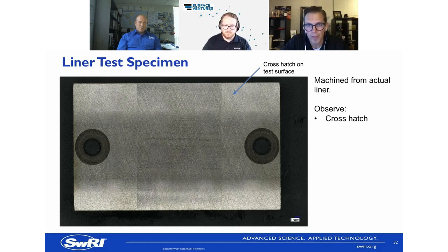And that was pre-run-in. Now with both coatings, we saw the RPK numbers drop down to the 5 to 7 range, and then the RK would drop typically to 25 to 30. But the RVK really didn't change that much. It may have been 45 to 50. Some of them were as high as 55. So with the variable hardness coating, it was a little bit less, but not a dramatic number less between the two. All right, thank you.